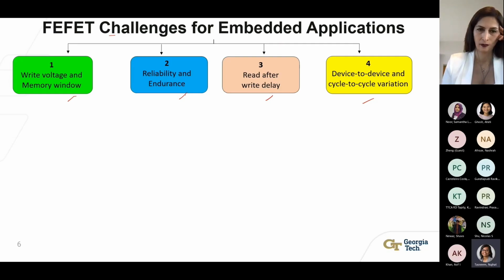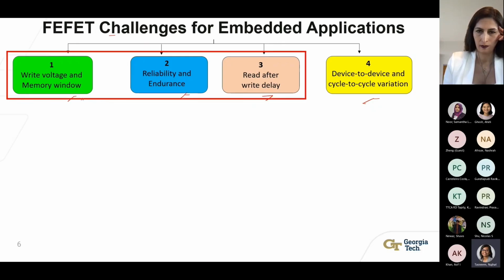The second one is that we want these devices to operate for a minimum number of endurance cycles, which is often a challenge. The third one is that there's a trade-off between speed and memory window, and we want these devices to operate with a sufficient memory window and a small enough read after write delay. The fourth one is that we want these devices to be identical to each other and to not vary in time, even after a decent amount of fatigue cycling. In my PhD, I focused on the first 3 challenges, denoted by this red box here.